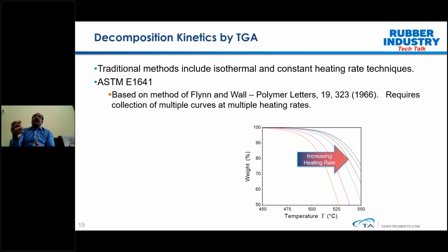And as I told you, decomposition is kinetic, so it always depends on the heating rate and the time. If you are doing it at a slower heating rate, the material will decompose at a lower temperature. At a faster heating rate, you can see clearly the decomposition will shift to a higher temperature, and that is because of the kinetics involved.